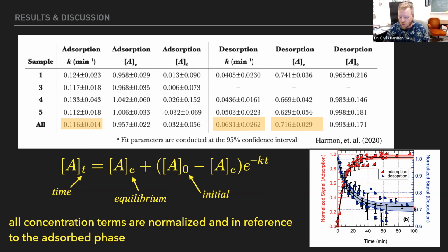And also what's really cool, not shown in this presentation, but my student, Megan Wright, was doing some of these experiments and then decided to close the drift cell and walked away and came back 24 hours later. And 24 hours later, she recorded a spectrum and it was still showing this 70% acetone coverage, which is really impressive when you think about it, because if you know anything about acetone, it evaporates if you look at it funny. And so the fact that 70% of it was still remaining stuck to the surface is a significant result.